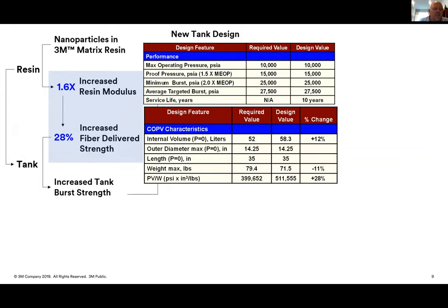So what we typically do is start with the resin. We do some small-scale tank development, as shown on the left, and get a nice improvement in fiber-delivered strength. Then we go into the design portion, where we ask what we can do in terms of removing weight and increasing volume for a tank that is set to burst at about 25,000 PSI with some known parameters. Out of this comes the result that, as shown in the table, you can change the internal volume. You can improve the efficiency of the design by increasing the volume and lowering the weight, taking very expensive fiber out of the structure.